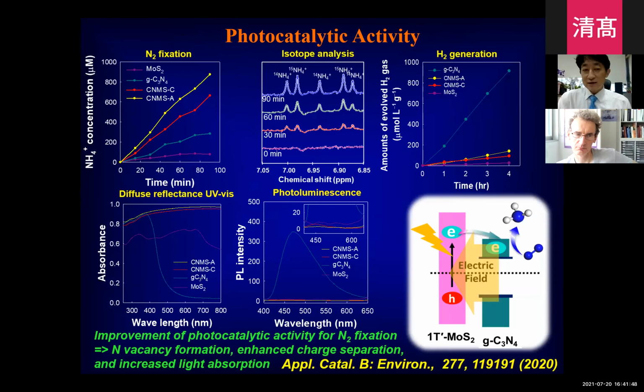Also, the resulting material was applied as a photocatalyst for nitrogen fixation. Nitrogen fixation gives the production of ammonia. As you can see here, the hybridization is very effective to enhance the nitrogen fixation reaction activity of the carbon nitride. From the isotope analysis, we confirmed the fixation of atmospheric nitrogen into ammonia. Actually, nitrogen fixation occurs by the photoreduction process. So hydrogen generation is the competitive reaction to the nitrogen fixation, but in contrast to the nitrogen fixation, the hybridization leads to the suppression of the hydrogen generation.